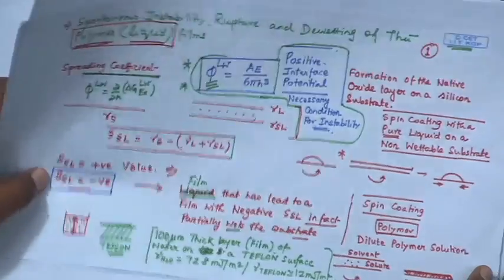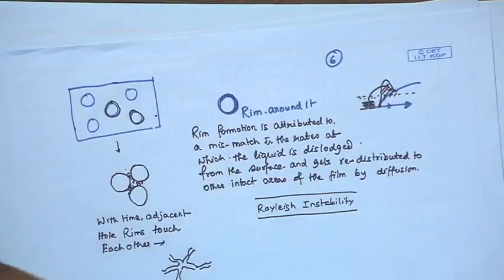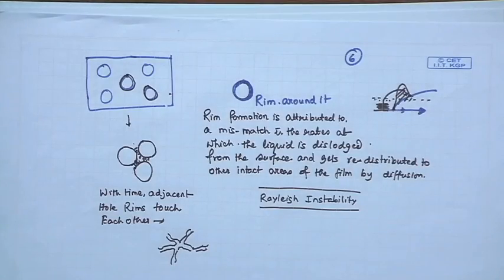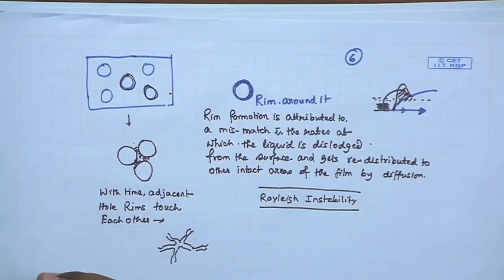Okay. So, now coming back to the issues related to dewetting, we had discussed quite a few points. We now know that the spontaneous instability observed in a liquid film is a long wave instability. We also know that before the film ruptures, there is a competition between disjoining pressure, which tries to destabilize the film, and surface tension driven Laplace pressure, which tries to stabilize the film.